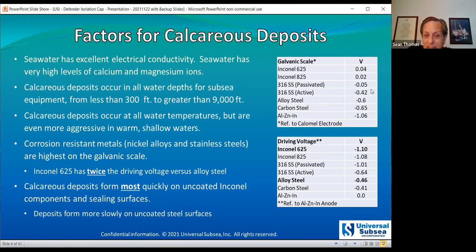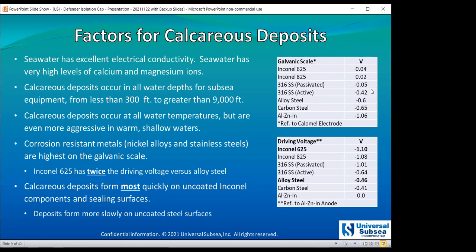So that's very clear there. The driving voltage for Inconel versus the aluminum anodes is more than twice as high as alloy or carbon steels. The consequence is that cathodic protection systems will be predisposed to deposit calcareous deposits on the Inconel surfaces first. They'll build up more quickly on Inconel than on alloy steel. And for surfaces like any sealing surface, we see very undesirable deposits on the sealing surfaces.